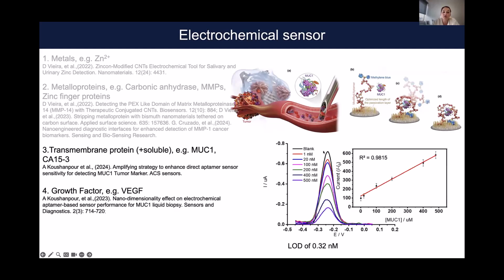And we show that we were able to measure a limit of detection. That means that the minimum concentration of mucin 1 present in the blood that we can measure with this system is 0.32 nanomolar. Okay, so it's a very low concentration of mucin 1.